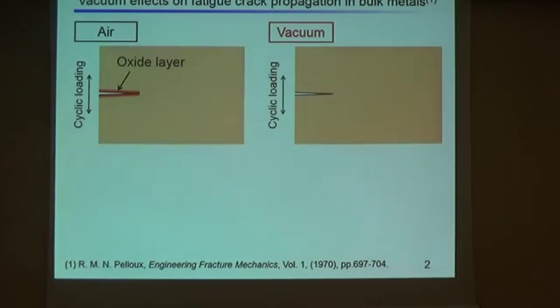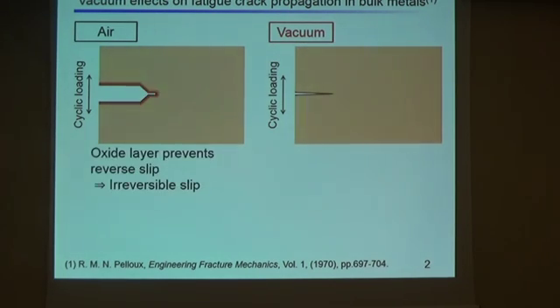It is well known that vacuum effects are observed on fatigue crack propagation properties in bulk metals. Generally, the fatigue crack propagates mainly by crack tip blunting and resharpening in bulk metals. And in air, fresh surface oxidation occurs at the crack tip in the loading process. This oxide layer prevents reverse slip in the unloading process. Therefore, at the crack tip, irreversible slip occurs during cyclic deformation, leading to fatigue damage accumulation at the crack